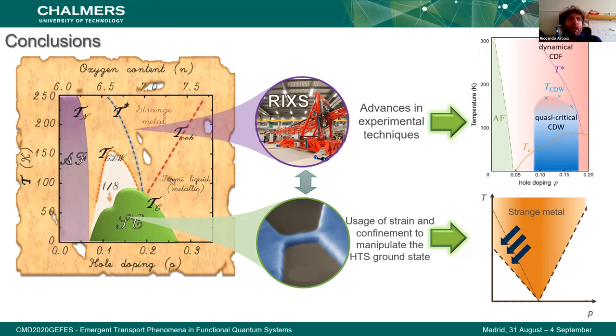It's very, very similar. The difference, apart from the correlation length, is given by the energy associated to this phenomenon, because the charge density fluctuations are dynamical. They are really associated to a finite energy in the order of several millielectron volts. While going down in temperature to the charge density wave, we are studying a phenomenon which is quasi-static, that would become static in the absence of superconductivity because this is a critical phenomenon. So when approaching zero temperature, you would expect this phenomenon to become completely static. But of course, superconductivity goes against this evolution.